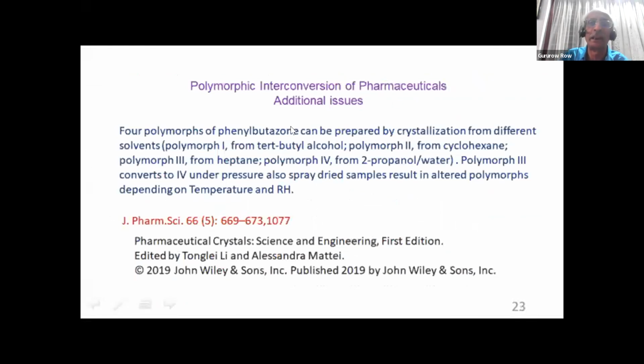Another example which I want to take is from the interconversions of pharmaceuticals. 4 polymorphs of phenylbutazone. They can be prepared by crystallization from different solvents. Polymorph 1 from tertiary butyl alcohol, polymorph 2 from cyclohexane, and so on. Polymorph 3 converts to polymorph 4 under pressure, and also spray-dried samples result in altered polymorphs. So these are all the observations that are made in the pharmaceutical industry.